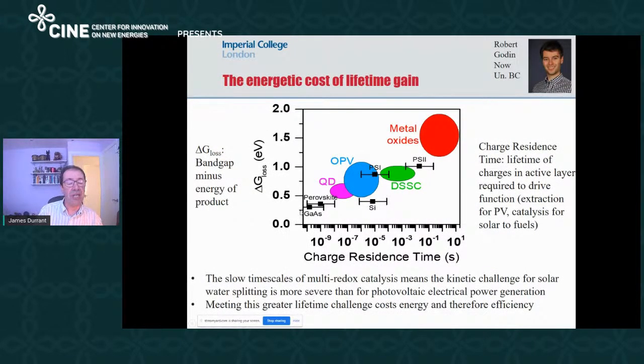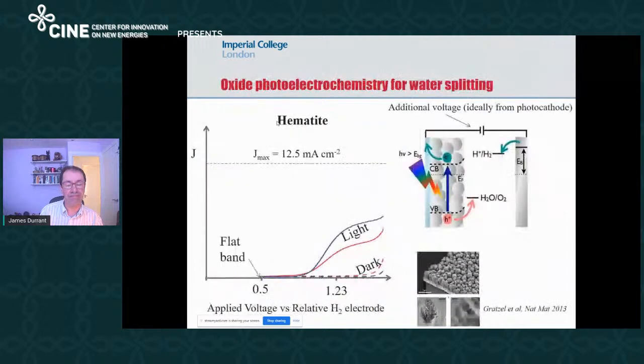Another way of drawing this is to look at the energy loss between the photon excited and the energy of the product versus how long it has to live to drive chemistry or to drive function. And you can see that perovskite cells and gallium arsenide down here have a small energy loss and very rapid extraction of charge to the external circuit. Here's photosynthesis, here's dye cells, and here are metal oxides trying to oxidize water. And you can see the lifetime required to drive the catalysis is slow, and the energy loss is large. And so much of my talk is around this kinetic challenge, how we can understand it, and how we can try to think about making it less severe.